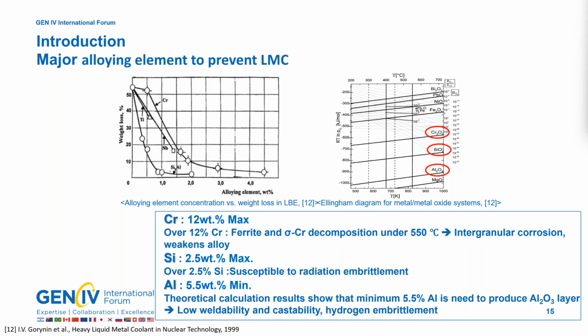Third, the aluminum content should be over 5.5%. Theoretical calculations indicate that a minimum of 5.5% aluminum is needed to produce an aluminum oxide layer. However, high aluminum contents can cause low weldability and castability and may lead to hydrogen embrittlement.